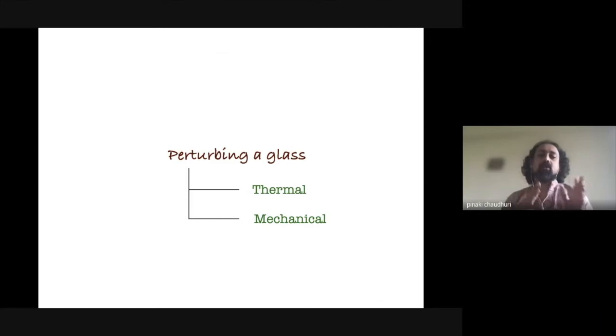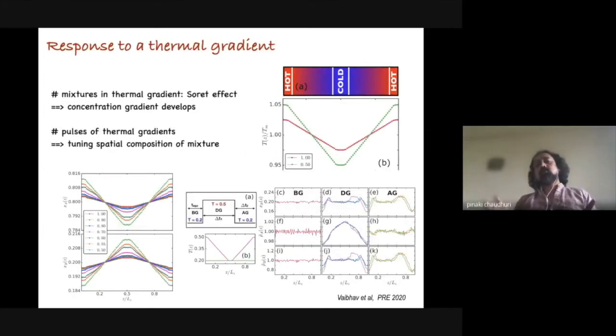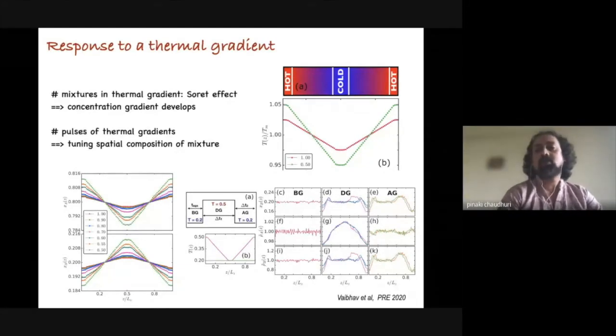So, in the context of this high-dimensional energy landscape and certain non-equilibrium properties like the aging properties of a glass, what I'll do next is perturb the glass, and then we will look at how this glassy system responds to either thermal or mechanical perturbation. If I do a thermal perturbation, what we do is apply a thermal gradient in this glass. If you look at the top right-hand corner, you have a zone which is hot, followed by a zone which is cold, and then again a zone which is hot. And this sets up a temperature gradient inside the system.